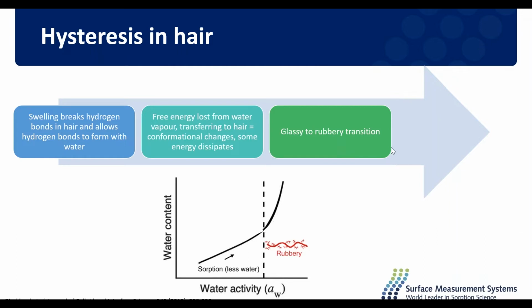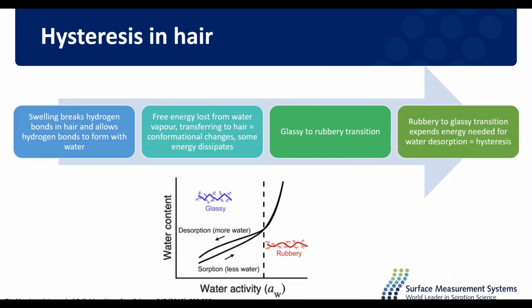And when the water is desorbing, once we go through our rubbery to glassy transition, there is not enough energy for water desorption due to that energy loss in the previous steps. And so that is what leads to a hysteresis. Now, this thermodynamic model for hysteresis has been shown computationally in cellulose water systems. So that has been proven, but as I previously mentioned, there hasn't been any experimental model for hysteresis to prove this so far.